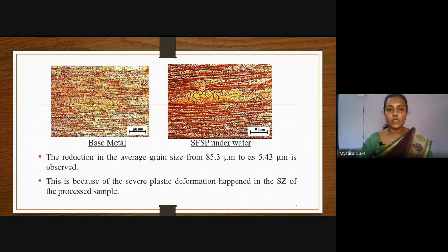And these are the microstructure SEM images that we got for different samples exposed to different mediums. The base metal had an average grain size of 85.3 micrometer. As you can see, it's very coarse. But exposing to water and friction stir processing reduced the grain size to 5.43, which is a very significant change. And this is possible because of the plastic deformation and the heat produced, and also because of the cooling. With normal friction stir processing, you could reduce the grain size, but not to this amount. Only because of this cooling could we obtain such a significant decrease in the grain size.